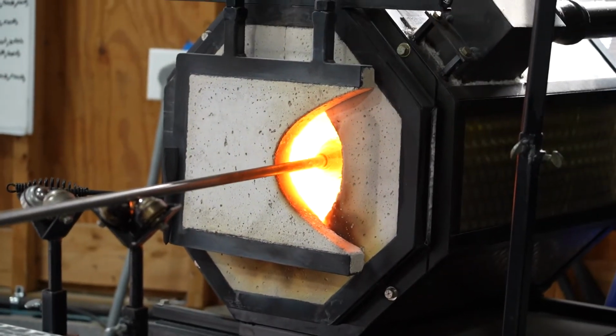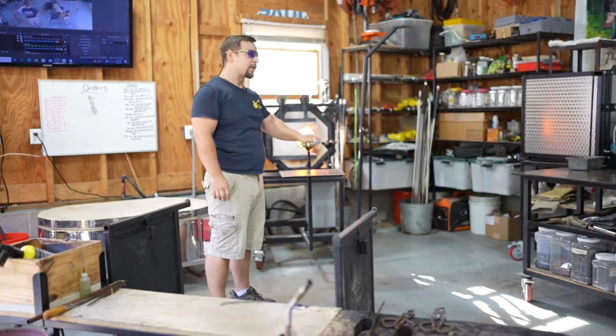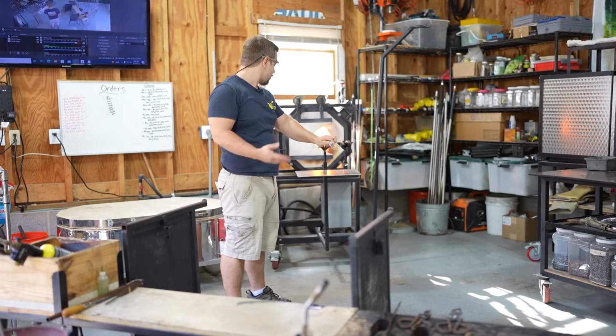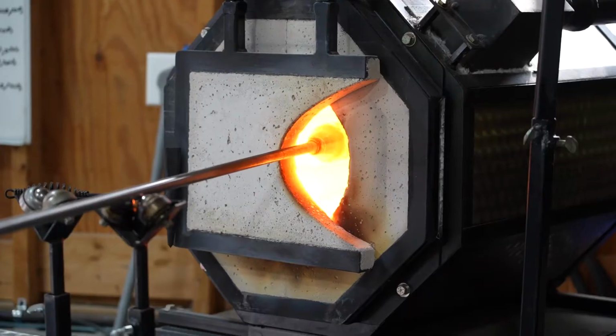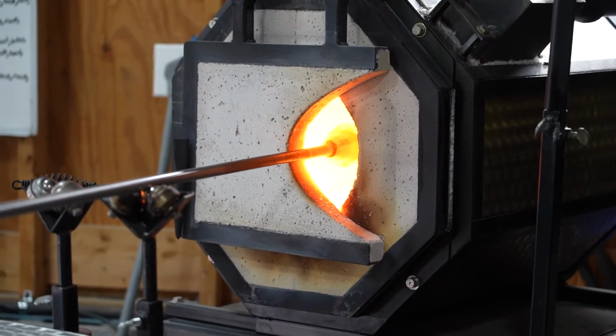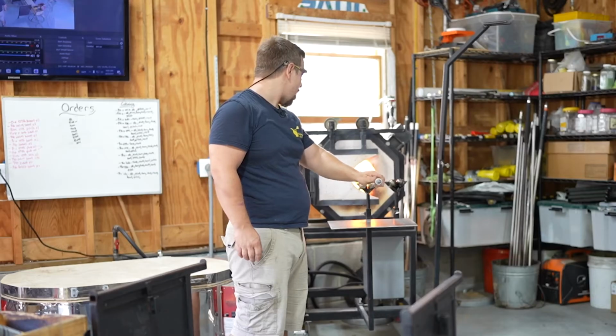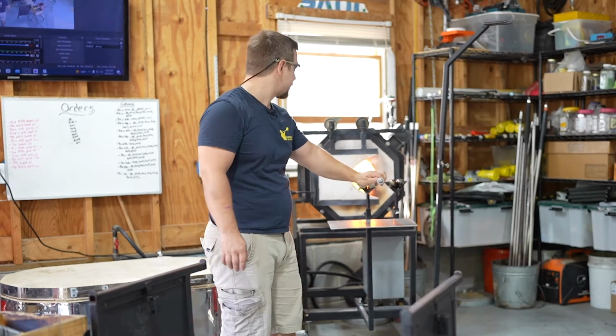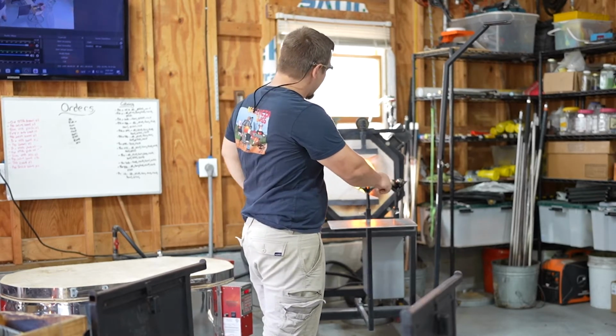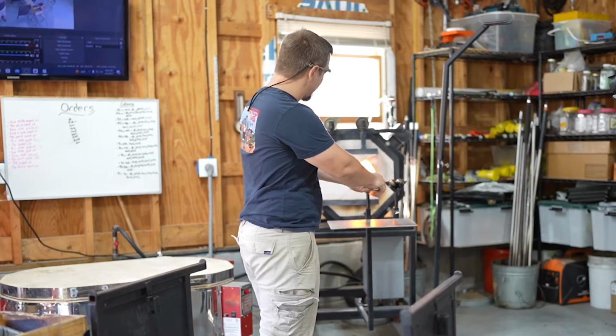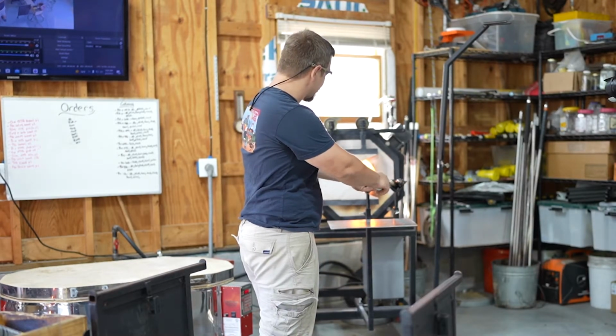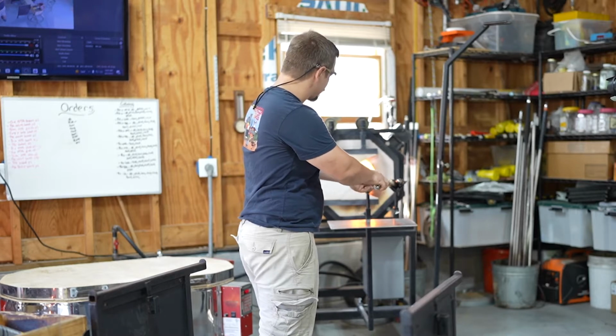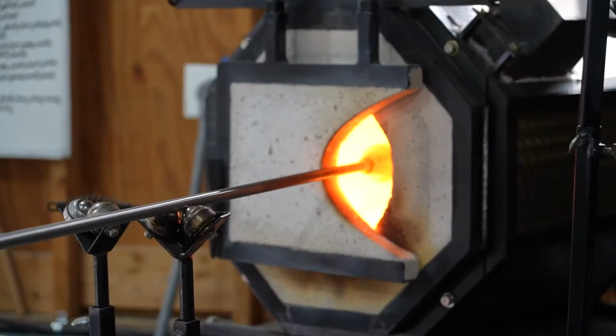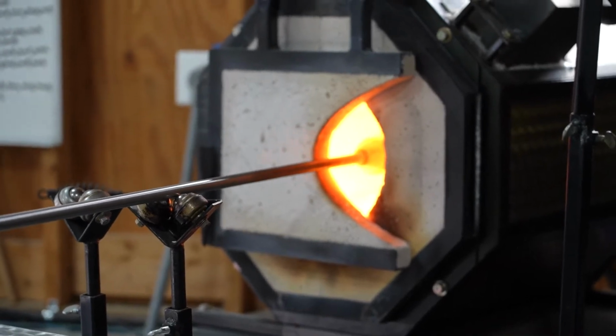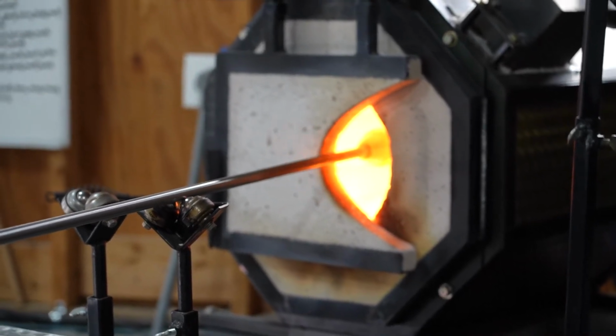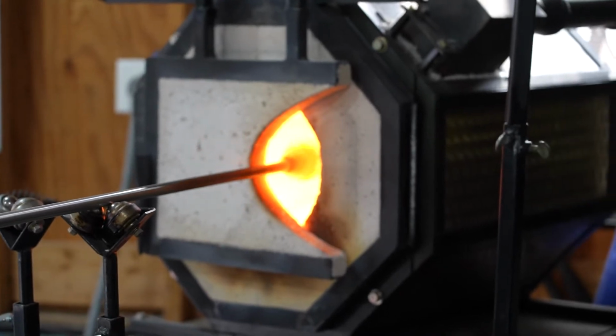This reheating furnace runs a little bit hotter than the reservoir, also a little above 2,000 degrees. And it doesn't run 24/7, but it gets hotter when we need it for the working purposes. None of the glass that's on the pipe will be below 1,000 degrees at any point in the process. Otherwise, it'll start to contract unevenly, and that stress will make the glass crack. Very similar to what you may have seen if you've ever dropped an ice cube into a glass of water.